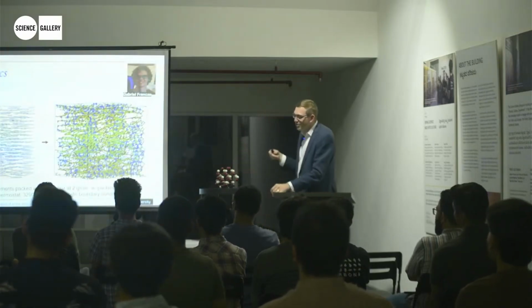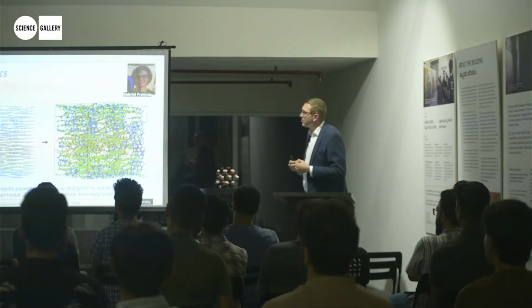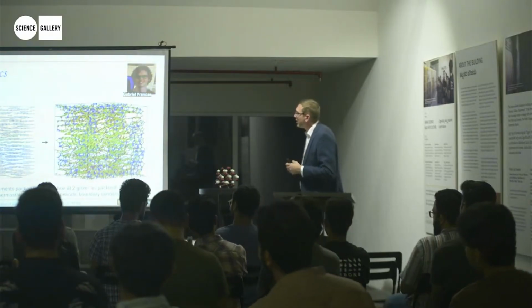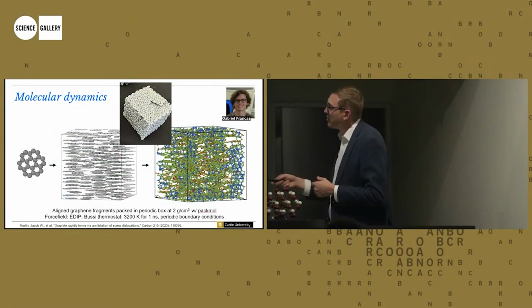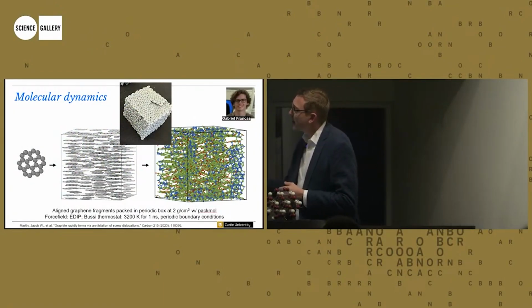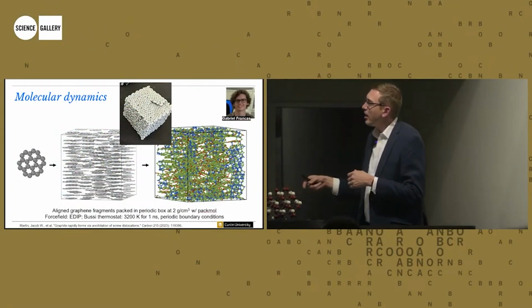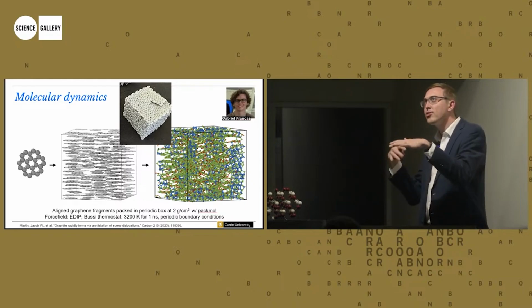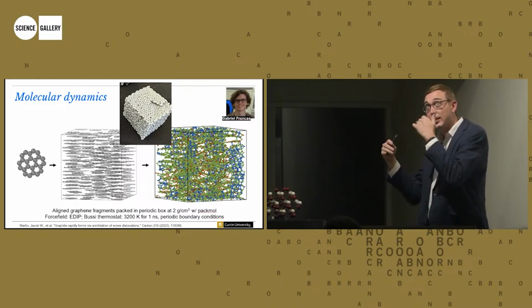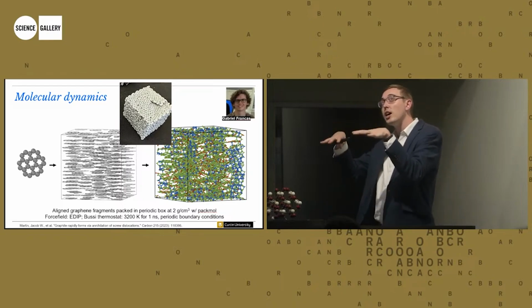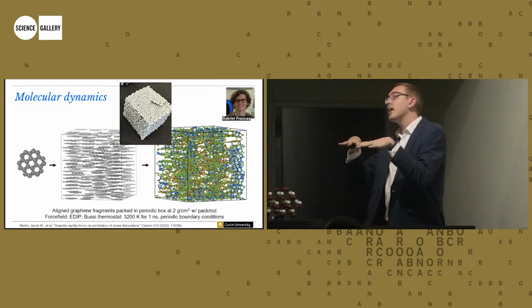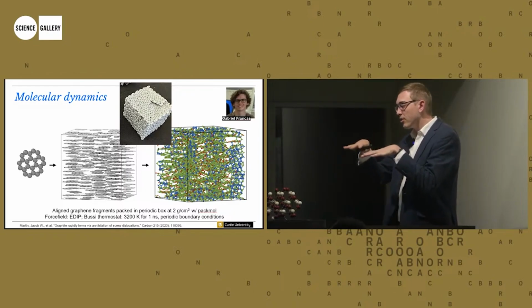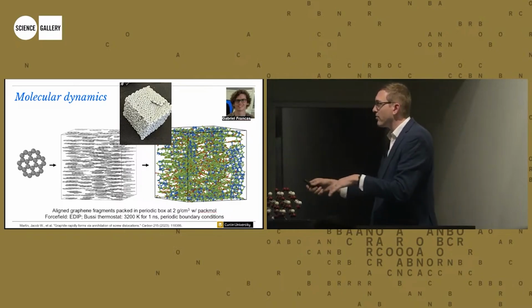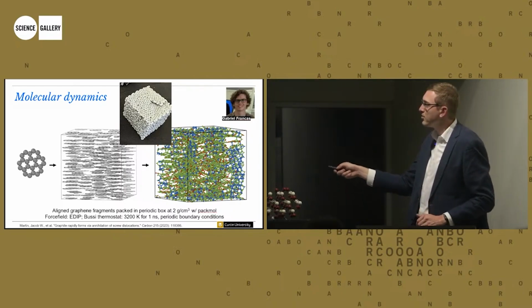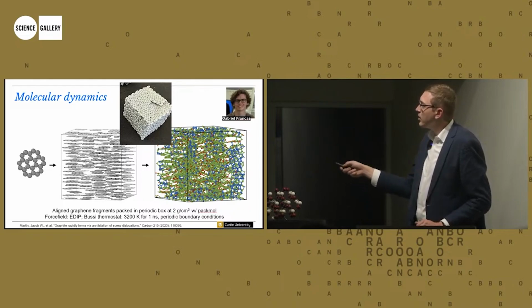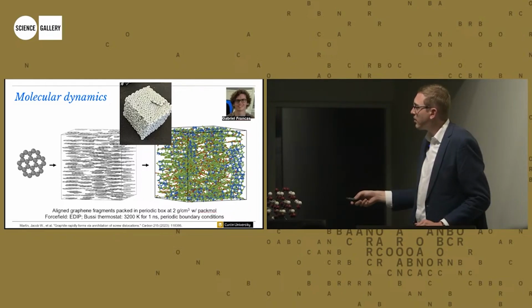So we wanted to use our virtual experiments, our simulations in the supercomputer, and we had an honours student, Gabriel Francas. So we put molecules or small fragments of graphene inside of a box, and we cooked it. We thought, okay, this is sort of like how graphitizing carbon forms. You get molecules that sort of align like a liquid crystal, and then that alignment means that when it is cooked, it can then form the graphite. So what we did is we did the same thing. We formed this aligned phase, and then we used molecular dynamic simulations.